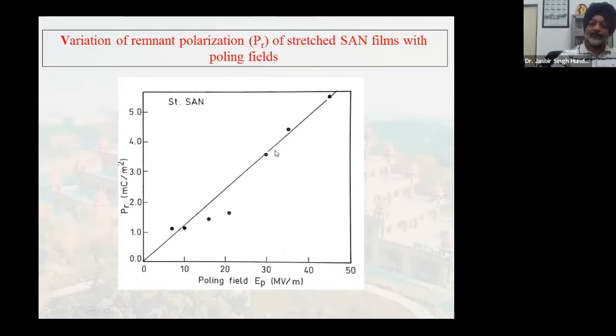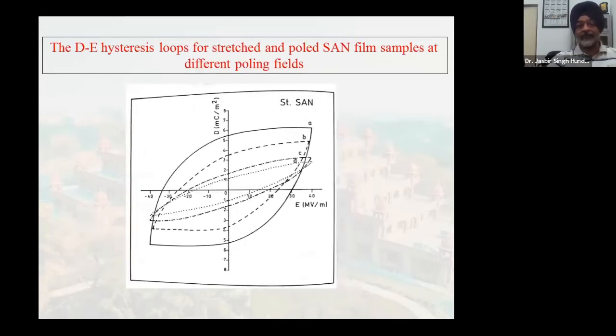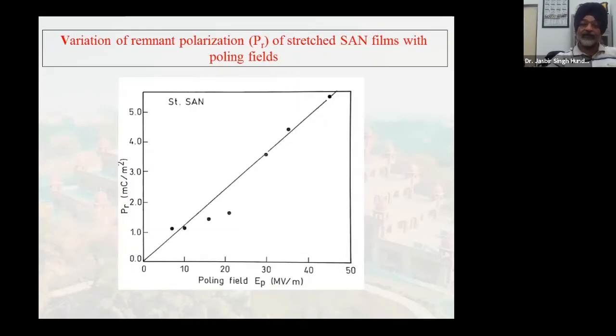If you consider 1, 2, 3, 4, 5 points out of 7 or 8, we find that polarization is proportional to the poling field. So once again we are trying to prove that whatever polarization, piezoelectricity or ferroelectricity we have in these films is due to dipoles, not due to anything else. Because in the case of dipole polarization, polarization has to be proportional to E, right? So this is what we had from here.